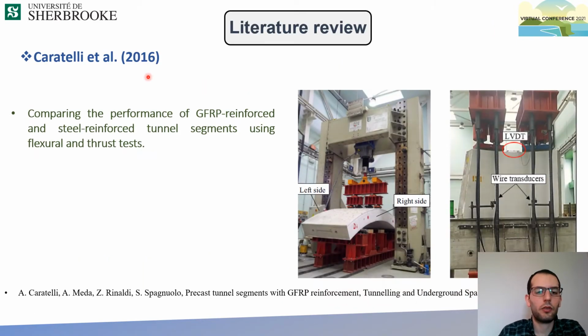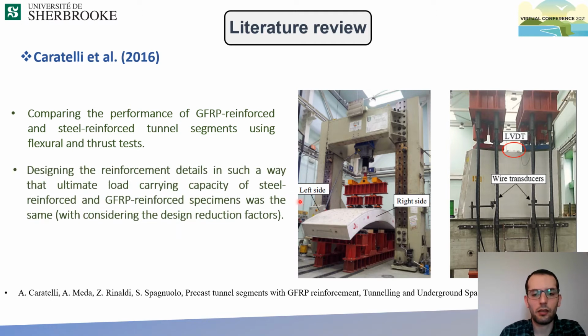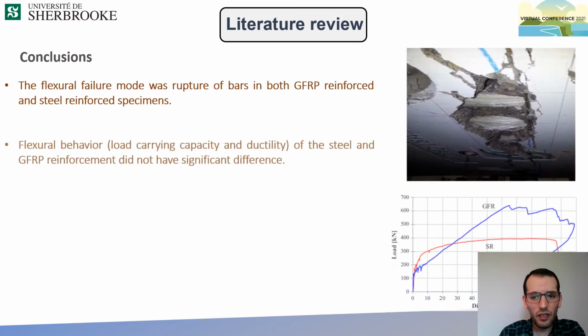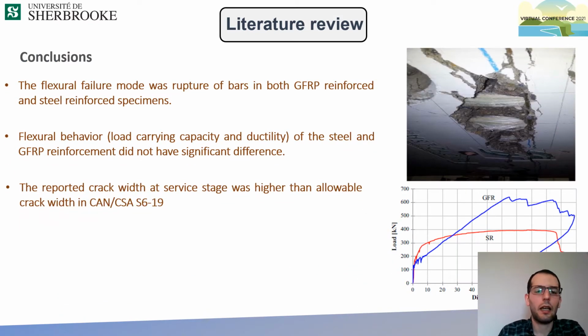The first study that used this type of reinforcement in tunnels was in 2016, by Caratelli et al. They compared the performance of GFRP reinforced and steel reinforced tunnel segments using flexure and thrust tests, and designed the segments to have almost the same capacity. But they used a smooth GFRP bar in the specimen. They observed a bar rupture failure mode, and they concluded that the flexural behavior of these segments is not very different, but the reported crack width at service load was higher than the allowable crack width in the standards in